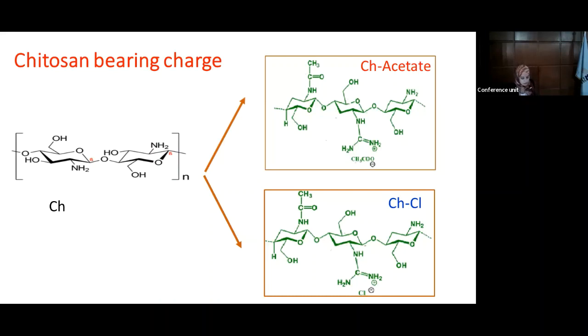They dissolve chitosan in acetic acid or even hydrochloric acid, and after that they let it interact with cyanamide. Then a cationic group is attached to the amine group in the chitosan. This group, we call it the guanidinium group. And afterwards, depending on the acid we dissolve it in, we have ions of acetate group or chloride group. Hereafter, I will call my derivatives chitosan-based acetate or chitosan-based chloride.